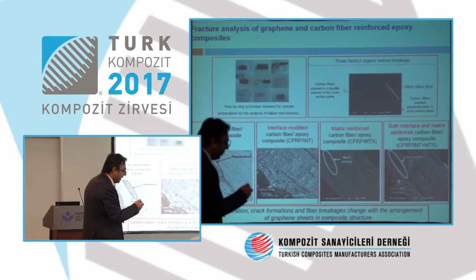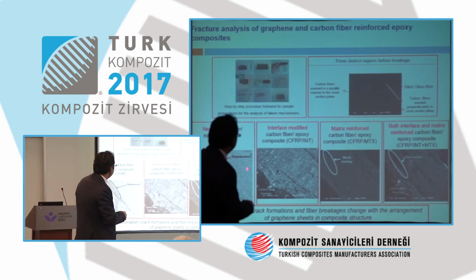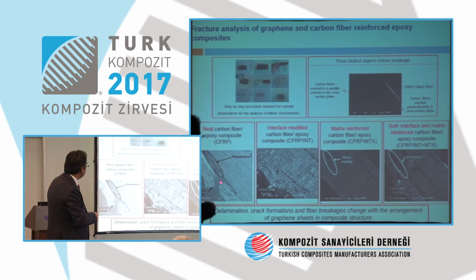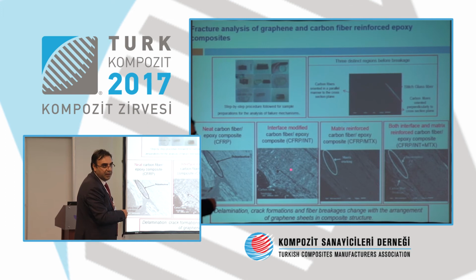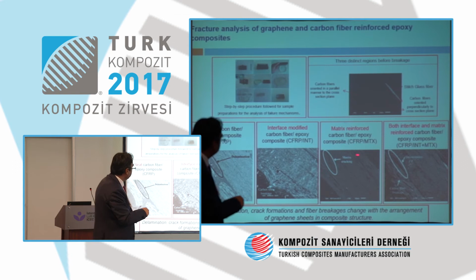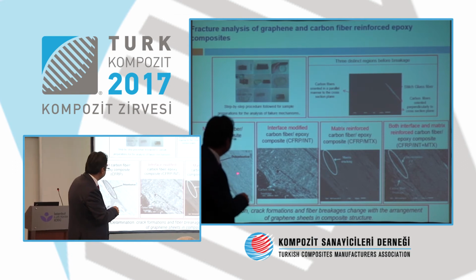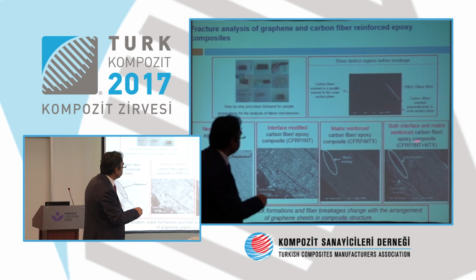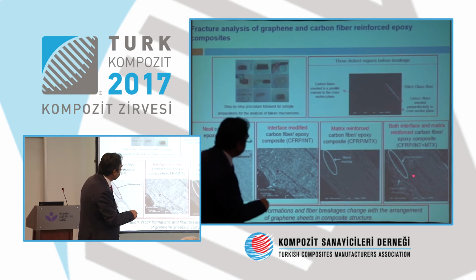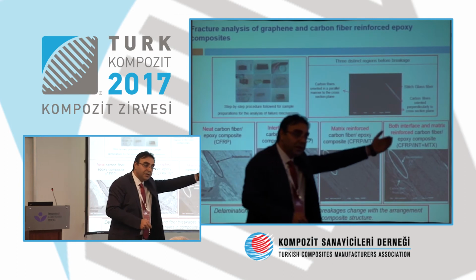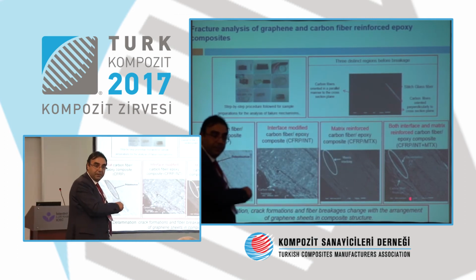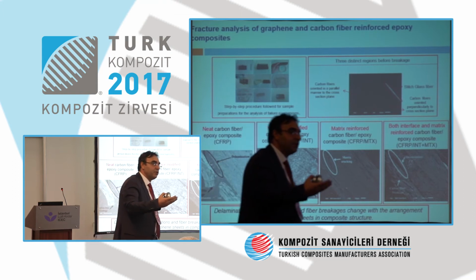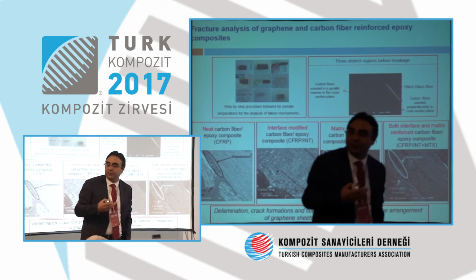And then we look in detail at the fractured surfaces, and you see that this is the neat one and it is being delaminated because you have a weak interface. And then if you improve the interface, it is strengthened, so there is no obvious delamination. This is matrix reinforced, and it prevents the cracks in the matrix with respect to the others. And this is both interface and matrix, and there is delamination, but this happens far beyond the force that we applied onto this one. So you are increasing the performance of your matrix and also increasing the performance of the interface.